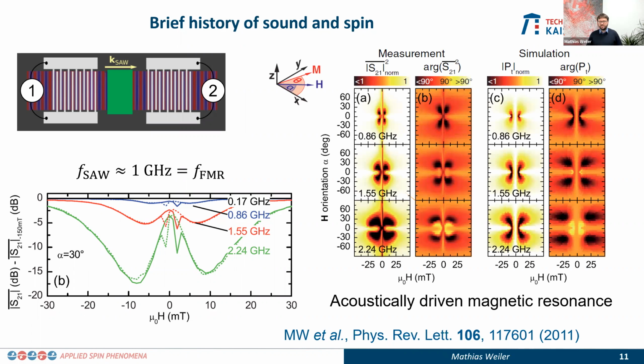What distinguishes this observation from the previous ones is that there is a very peculiar angular dependency of this interaction here. And that dependency of the acoustically driven magnetic resonance can be traced back directly to this approach originally proposed by Kittel, of deriving the driving fields of this interaction from the change of magnetic anisotropy that is induced by the oscillating wave.